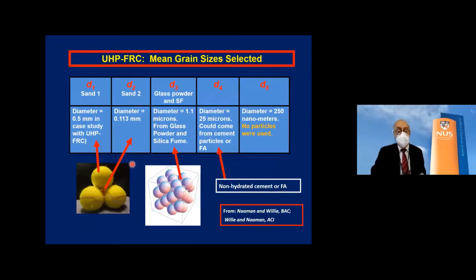Now, this is visually, some of these, the big sphere here is our 0.5 millimeter sand. The one inside is the 0.11 millimeter. The very, very small one is the 1.1 micron. And then we counted that there might be some non-hydrated cement that can occupy, in the 25 micron range. And this was nanoparticle we didn't use.